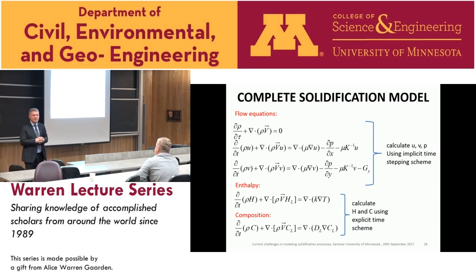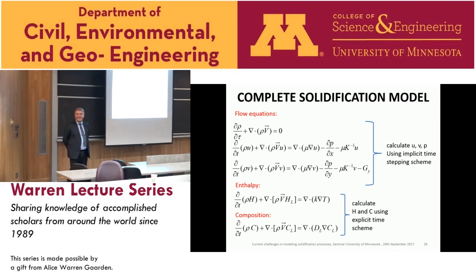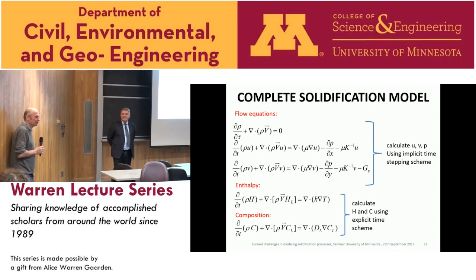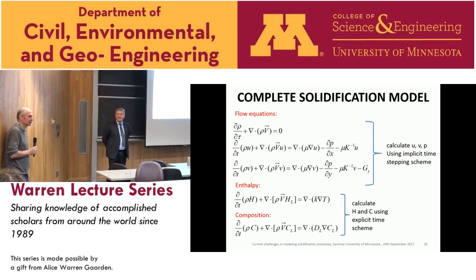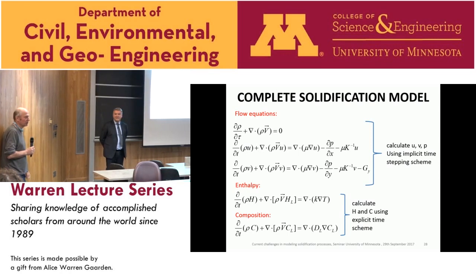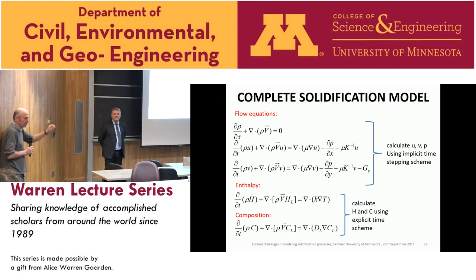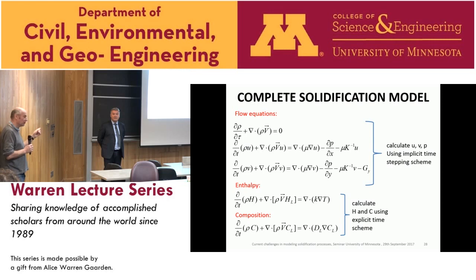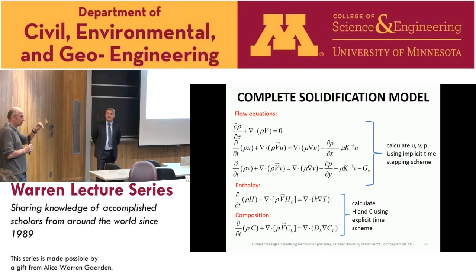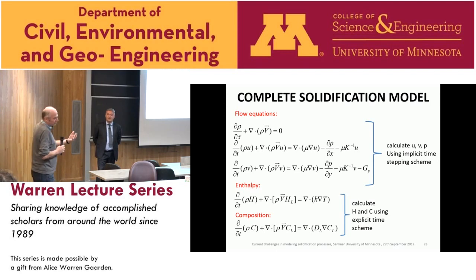Thank you. Can I add something to that? People have looked at that. Typically they use the K-epsilon model, and typically in modeling steel casting processes, the turbulence switches off very quickly once you get into the mushy region. So it's just maybe at the very outer fringe. And I think what Igor was saying is that in terms of controlling the thickness of the mushy region, the solutal component is much more relevant on a larger scale. But people have looked at turbulence in these models.